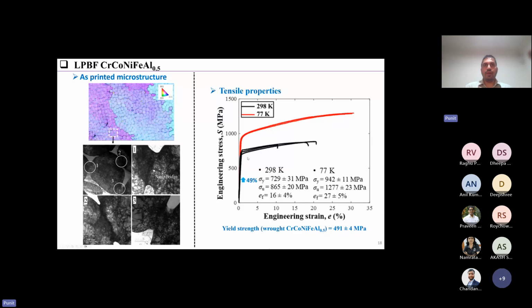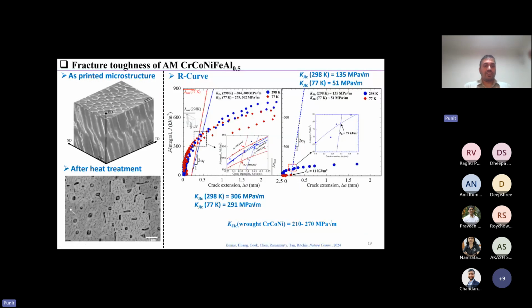So we wanted to look at the fracture resistance of this alloy. And for evaluating fracture resistance, we go through this process of generating the R curve, where we measure the load line displacement, and based on that we calculate J values for each step of crack growth. And if we draw a blunting line through these R curves, we can get this J1C value, which we can convert to KJ1C through K and J equivalence. And in this material, what we see is that fracture toughness is about 300 megapascal root meter at both room temperature and cryogenic temperature.